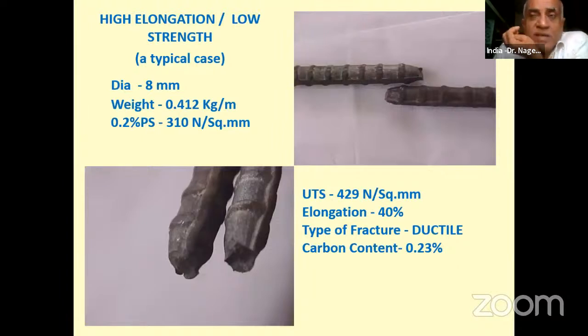Now, sometimes the bar fails. Why does it fail? Because the quenching activity while manufacturing the TMT bar is not proper, so these things can occur. Here the diameter is 8 mm, and 0.2% proof stress is only 310 MPa, which is nothing but mild steel.